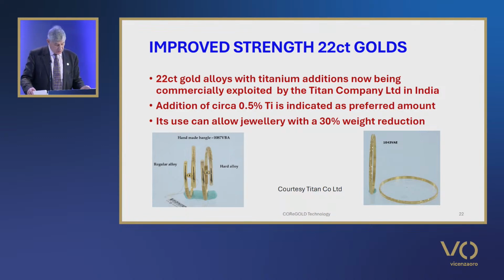The commercial use of a 22-karat gold alloy strengthened by titanium, based on this work by the Titan company in India, has allowed jewellery products to be marketed that show a 30% weight reduction compared to conventional 22-karat gold alloys. The figure on the bottom left of the slide shows a hollow bangle in their new alloy. That on the right shows a solid bangle. And my understanding is it's about 0.5 weight percent titanium is the alloying addition.